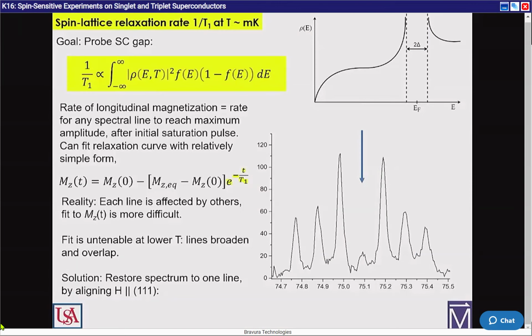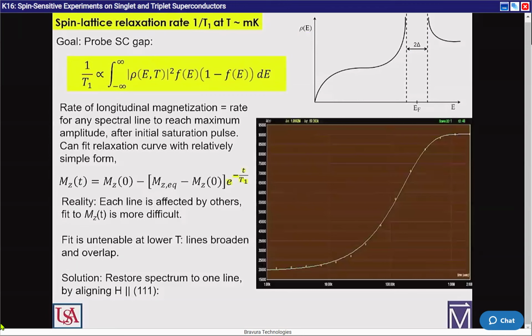watching the rate at which any one spectral line evolves with time after an initial saturation pulse. And what you would expect from a single line is that you would have an exponential decay factor right here, which gives a nice fit, and there is where you get your 1 over T1 from. In reality, this is not always easy to do. In reality, lines interact and affect each other, and the fit is not as straightforward.